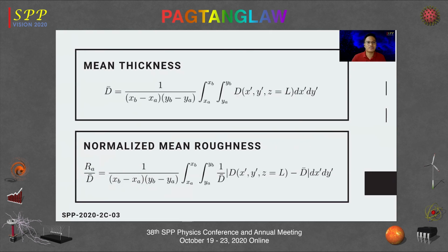Now, the normalized roughness, on the other hand, just describes the deviation of each individual point along the surface of the substrate from the mean thickness. And we normalize this mean roughness with respect to the mean thickness in order to isolate the effect of decreasing thickness as you move away from the center of the plasma plume.